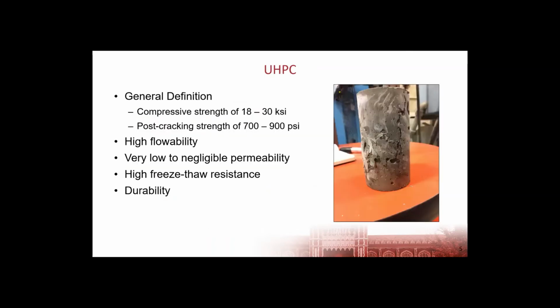And as has already been discussed, UHPC is a great material, has a lot of potential for a lot of different things. It's characterized by its high compressive strength. Here, using a more general definition, between about 18 and 30 KSI is what you will typically see as UHPC, and then also has that great post-cracking tensile strength that we discussed in the previous presentation. It's very flowable and is able to get into some complex shapes, which is wonderful when we're talking about repairs and rehabilitation. And we'll talk about that a little more later on in this presentation.